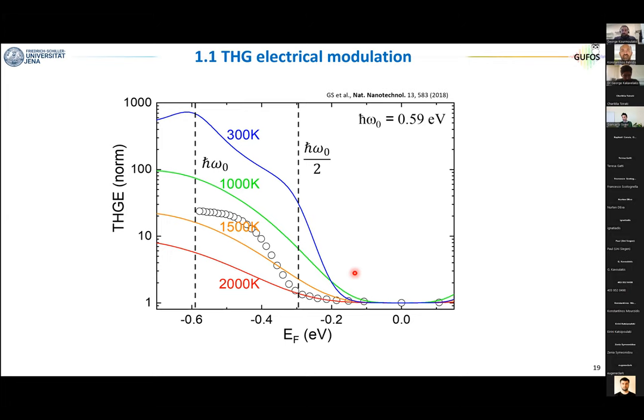And this increase in the temperature is what eventually changes the efficiency of the nonlinear process. And since we know that the absorption of graphene is also gate tunable, because by tuning the voltage you can move between intraband and interband absorption, you see that as we cross this point, the experimental data do not follow any theoretical curve. This is because the theoretical curves are done for a fixed temperature, while the real experimental temperature changes as you change the Fermi energy.